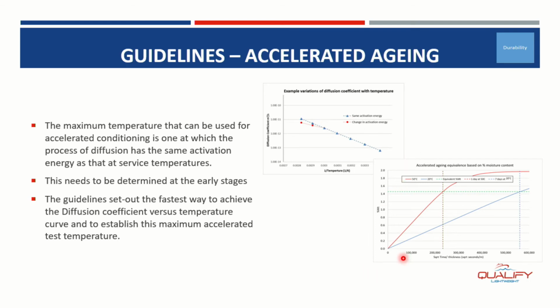So just carrying out normal gravimetric testing. This example shows 50 degrees and 20 degrees. Here, if we look at equivalent moisture content, that's the average amount of moisture in the joint at a given time. To achieve the same level at 50 degrees takes 1 day, whereas it would take a week, or 7 days, at 20 degrees centigrade. So we can see there's a significant effect of accelerating the temperature, and it's the most useful tool we can look for accelerated conditions.